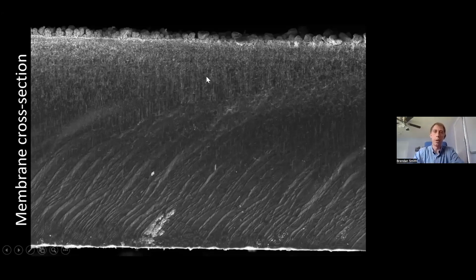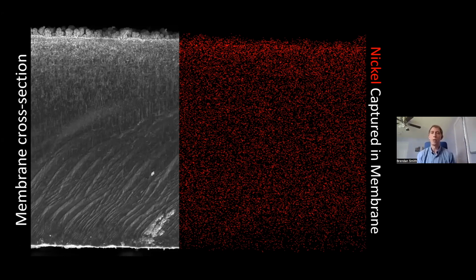What you can see here in these vertical gray streaks are the actual pores or channels running from one side to the other. And these largely pass all the way through the membrane, allowing that flow of dissolved battery solution or liquid to come all the way through. So what we do here is we apply a very specific voltage to the membrane. What this does is electro-extract specific materials from that complex flow. So in this example, we're electro-extracting nickel. And you can see via microscopy, following the experiment, we crack the membrane open and look at the cross-section, that only nickel is fixed within the material structure itself.